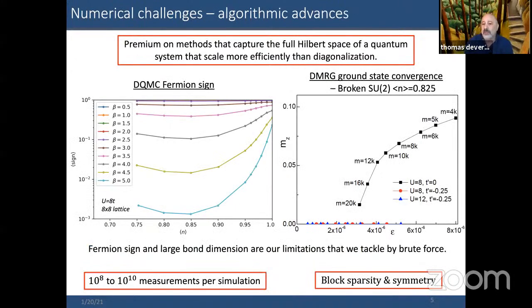So here is the problem that we're dealing with, the numerical challenges, and where a lot of the algorithmic advances have been made in the last decade or so. Of course, these algorithms have been around for quite a while, and they suffer in two important ways. One is the well-known fermion sign problem. This is shown on the left-hand side, which is the average sign plotted as a function of filling or doping on an 8x8 lattice for different values of inverse temperature beta. You see that when the average sign gets down to 10^-3, that means you have to work a lot harder. It doesn't mean that you can't get any good data. It means that you have to accumulate many, many measurements to deal with the sign being that small.